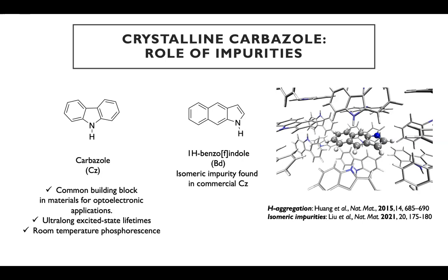and it's related to the photochemistry, or the photophenomena, that happens after exciting crystalline carbazole. Carbazole is a very simple organic molecule that can be used as a building block in many optoelectronic applications. And an interesting thing about carbazole is that it shows ultralong excited state lifetimes. It's something that is called afterglow materials. Essentially, you irradiate them, and after illumination, they stay emitting light for a long time. And the reason for that is not completely understood.